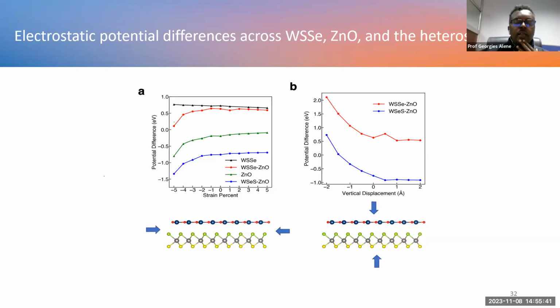Yeah, that's true. But the other thing is, when we have Janus transition metal dichalcogenide, because of these two types of chalcogen materials on the two different layers, this breaks the symmetry. They have a charge difference, and there is some intrinsic dipole moment which might assist the charge separation of the photogenerated carriers. So that was our intention, but I agree with you, it is also good to consider only the transition metal dichalcogenide, and it depends on the interest of the researcher.